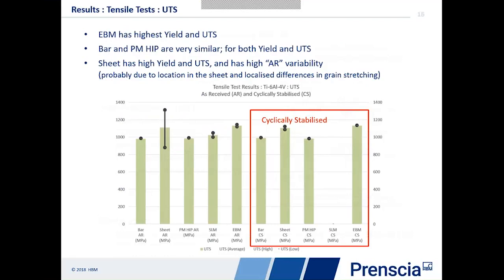So first of all, let's have a look at the tensile properties when we do these sorts of tests. Electron beam melting, first of all, appears to have the highest yield and UTS values. If we look at these plots below, what this is showing us is, in the red square, tensile tests which have been cyclically stabilized before testing.